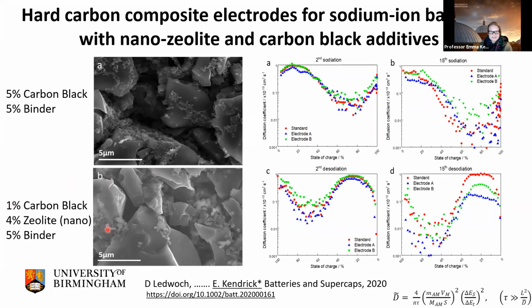If we put a small amount of this zeolite in and substituted it for the carbon black, although our overall resistance increased in our electrode, and these little white patches that you can see here are the nanozeolite that we've added, these bits here are the carbon black. We found that we could actually improve the diffusion coefficient over time compared to what we had. And whereas these low diffusion coefficients down here were still observed for the standard electrode, when we added a little bit in, we got slightly higher diffusion coefficients on this bottom plateau.